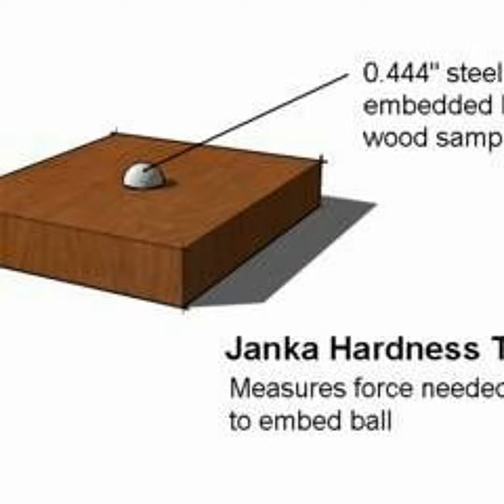And when you compare it to white oak, for example, they have very similar hardness Janka numbers. They have very similar density numbers. They are definitely different, though: white oak being ring porous, maple being diffuse porous, and that can contribute to the higher shearing strength. So you'll see how all these numbers start to interplay with one another. Because the pores are scattered all over the place and diffuse in a piece of maple, there's a lot more of that really dense connective tissue that makes the shearing strength dramatically higher.